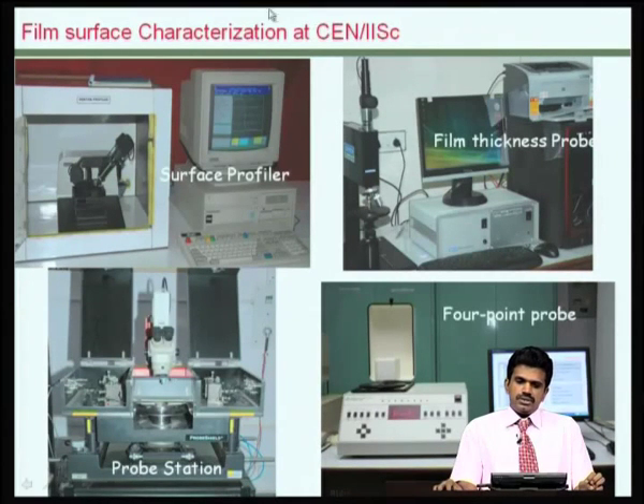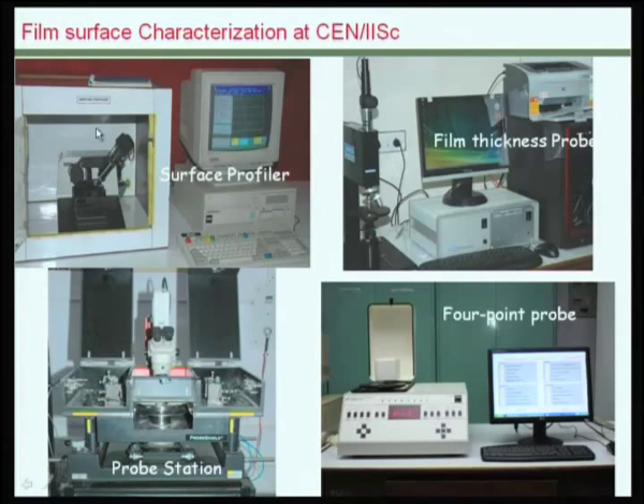The film characteristics that I have mentioned are evaluated using various instruments that are shown here. The thickness as well as the uniformity of the thickness can be evaluated using a surface profiler. What you see here is a contact type surface profiler, where there is a scribe which would actually move and its position is recorded, and based on the position of the tip of the scribe, one can determine the height of the surface of the film.